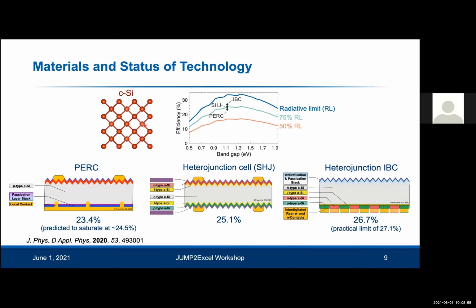So silicon, crystalline silicon has a crystal structure that you see here. It has the same crystal structure as diamond. So you have a tetrahedral arrangement of silicon atoms which form covalent bonds. So if you break these bonds, for example, by having vacant sites, or even just at surfaces, then you have dangling bonds which create defect states in the middle of the band gap. And that causes irreversible losses in energy through a process called Shockley-Read-Hall recombination. So a lot of the history of development of silicon photovoltaics was about addressing these defects, how we can process the materials to minimize the densities of these defects, as well as how to passivate the dangling bonds at the surfaces.